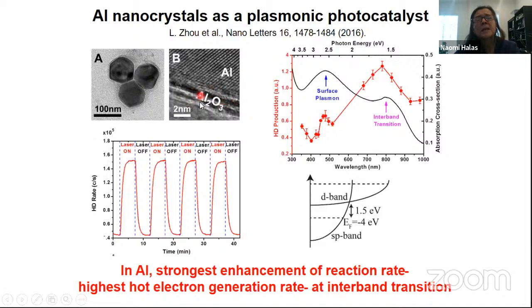So we're doing basically exactly the same chemistry, where we excite the nanoparticle and we generate hot electrons, and the hot electrons then transfer to make H2 minus, and then H2 minus dissociates. Now, what is a little different about this is that it turns out the actual plasmon of the aluminum is not as important as the interband transition. Of course, aluminum has a very different electronic structure than gold, and so there is an interband transition down around 800 nanometers in incident wavelength, around 1.6 electron volts, which has to do with the fact that there is an unoccupied state above the Fermi energy for the aluminum. And this is important for my argument later.